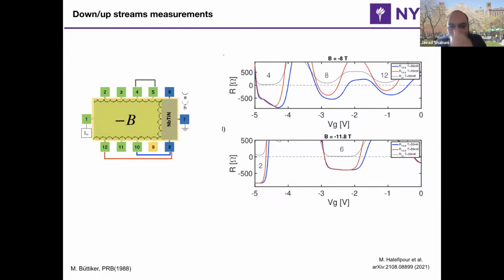And then the red is the longer path. And you see that this is slightly smaller because, I mean, it still is quite quantized at the value that the blue is also quantized to. If you look at 8 Tesla, which is the top graph, things are weaker. Even RXX is weaker. So the quantum Hall is not as well defined, or the gap is not as strong. Then you see that the blue line, which is the shorter path, is deeper than the red, for example, nu equals 2 to 8, right? But for nu equals 2 to 4, the state is quite strong. Blue and red are basically on top of each other in the middle of the quantum Hall state.